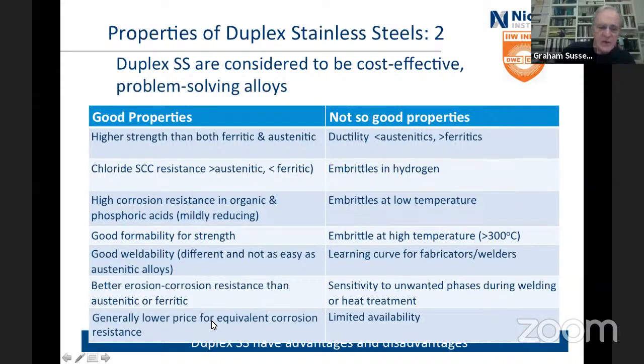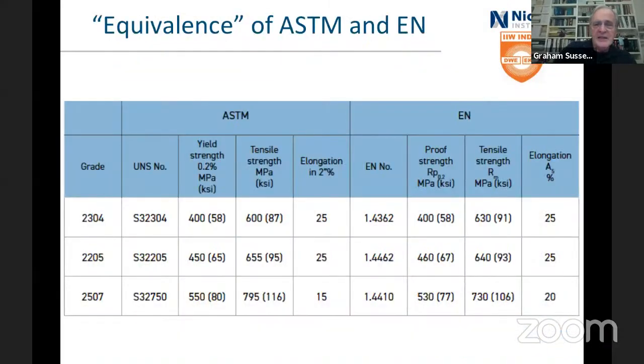And it's generally going to have a lower price for equivalent corrosion resistance. The reason for that is because it doesn't have lots of nickel in it. And the only little snag is that it's a bit harder to process out of the mill, and so there isn't quite the wide availability of it. It's growing, but it's still not enormous. It's still, you know, less than 5%. ASTM and Euronorm both have it in.